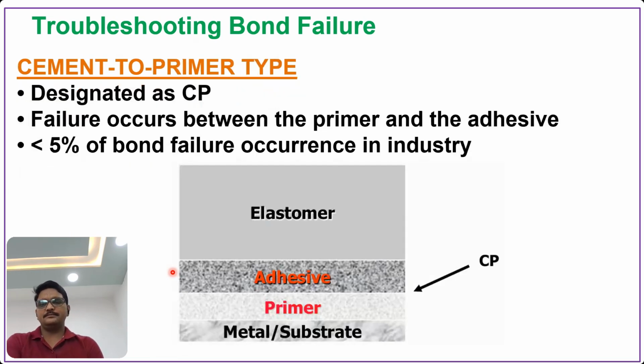Next is solvent entrapment in the adhesive film. It means we need to allow longer drying time between the adhesive coats. After the primer, we need to keep them properly dry, then we need to apply the cover coats. Another cause is a thick coat of primer. Maybe the DFT, dry film thickness of primer, may be more than 5 to 10 micron, maybe 25 to 30 micron or 40 micron like that.